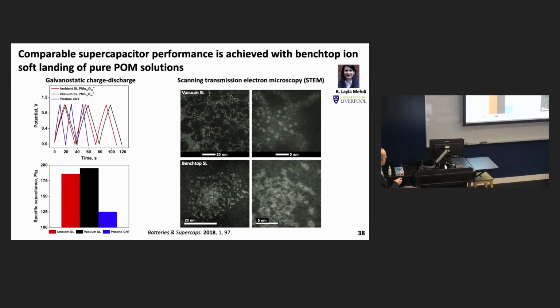In the benchtop soft landing, it's similar coverage. The morphology is a little bit different overall, right? You don't have these spidery distributions. You have more of an island with a higher density in the center and then going out. But nevertheless, when you go in and look, even at the highest density, you can still see individual atoms corresponding to the molybdenum and tungsten that's present in those clusters. And this is very different to that large aggregated crystallite matter that I showed you earlier in the slides, right? That was like 5 nanometers in size. You're still seeing atomically resolved species here.